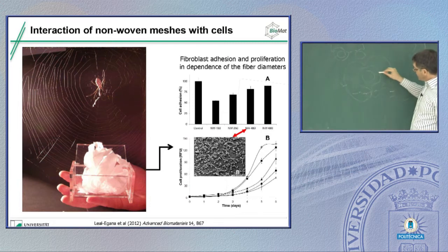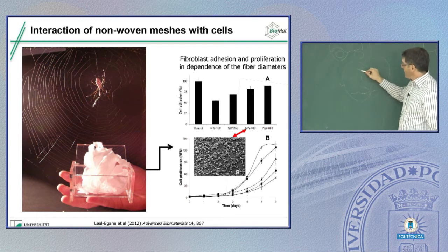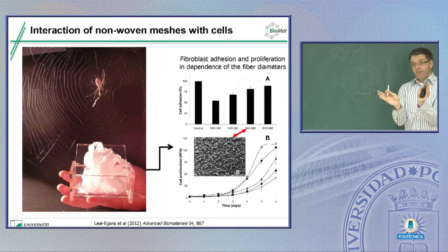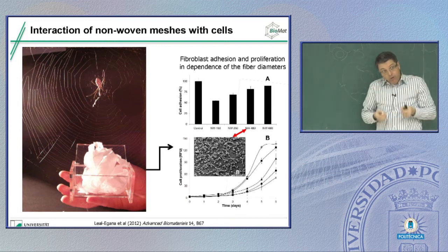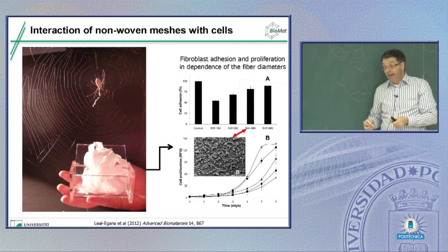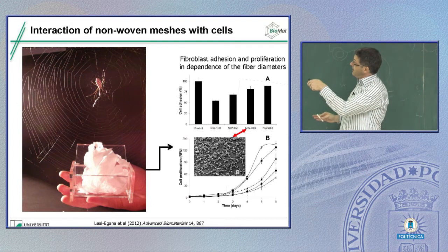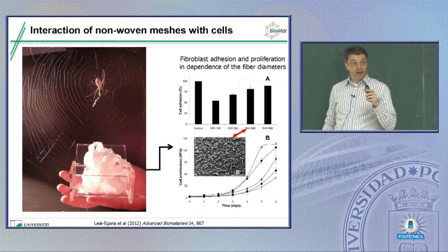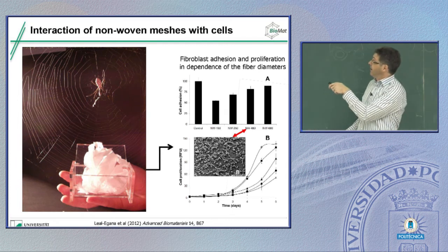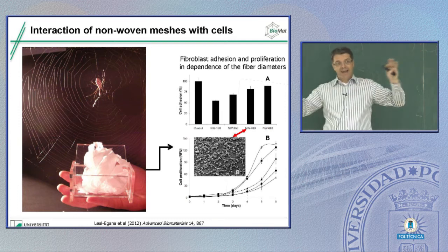Because, as I told you, there's always an interaction between the extracellular space and the cytoskeleton. So if they have a grip outside, they also can direct the cytoskeleton inside. And they pull, literally they pull on the surfaces and on the materials. And therefore also elasticity plays quite a dramatic role. And therefore there is really a very distinct influence of fiber diameter, because pore sizes here are in the micrometer range. They're in all cases quite high.